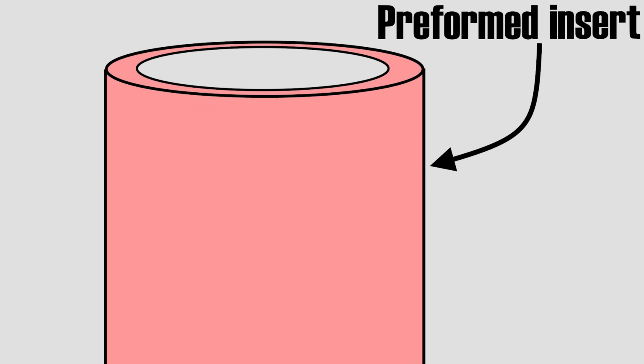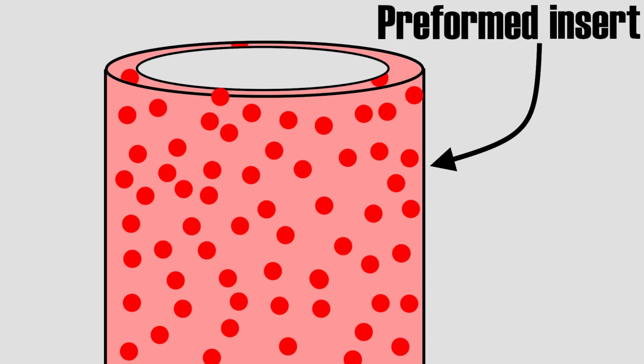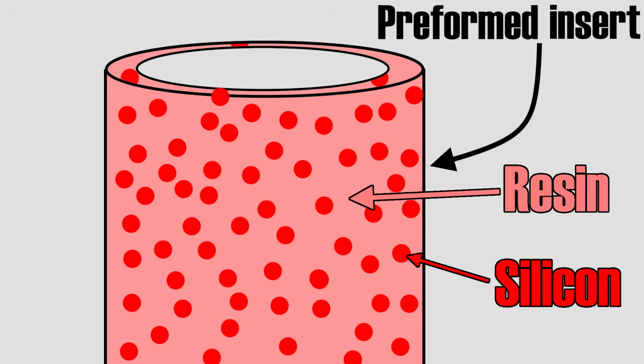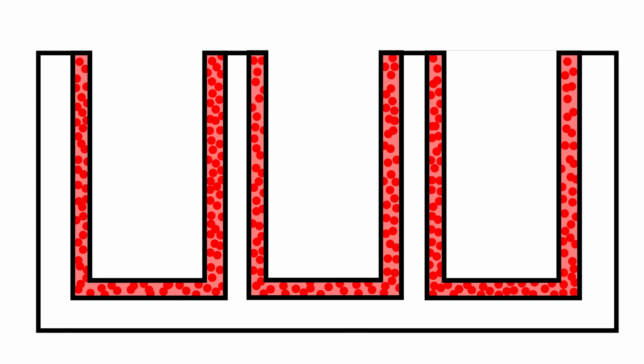So what Lokasil does is that it uses pre-made inserts, which are essentially silicon suspended in some sort of resin. These pre-made inserts are placed in the mold, and then the melted aluminum enters the mold. The high-temperature aluminum melts away the resin, and so what remains is a layer of silicon on the surface of the cylinder, the only place where you actually need it.